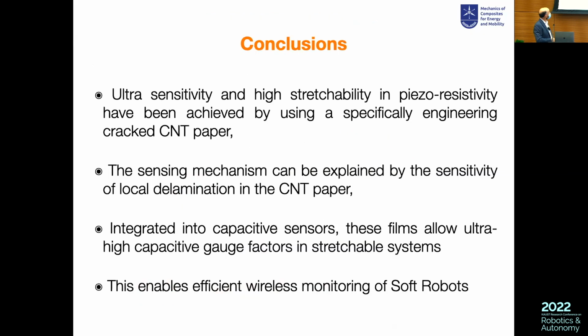So just as a conclusion, we develop ultra sensitivity and high stretchability in piezoresistivity by using a special engineering of CNT papers in this work. The sensing mechanisms can be explained by the sensitivity of the local delamination in the paper. You can integrate it into capacitive sensors, and these films are going to allow ultra-high capacitive gauge factor in stretchable systems, so you can have an efficient wireless monitoring for our soft robots or other applications.